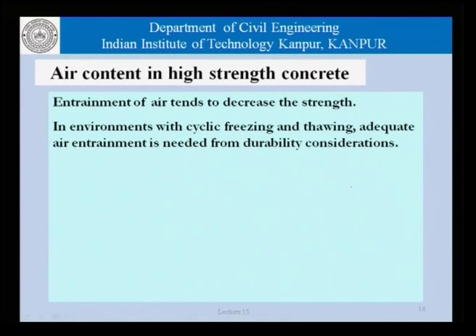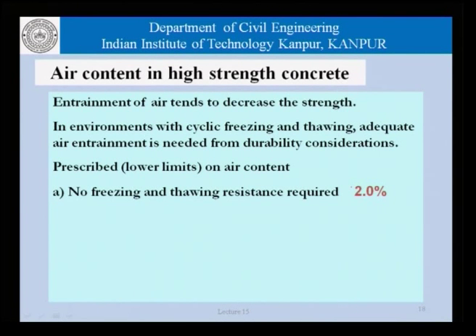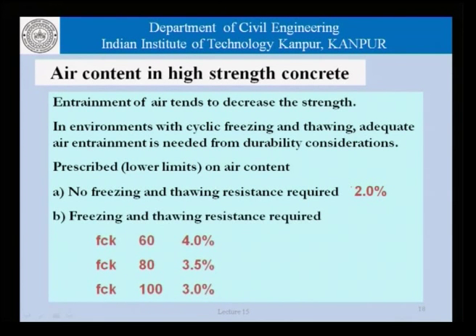Now, as far as high strength concrete is concerned, that is quite an unacceptable position, and therefore, we must try to control that. In environments with cyclic freezing and thawing, adequate air entrainment is needed from durability considerations, but prescribed lower limits on air content could be, if no freezing and thawing is there, then of course 2%, but in case freezing and thawing resistance is required, then we can see here that the air content requirement goes down as the required strength increases.